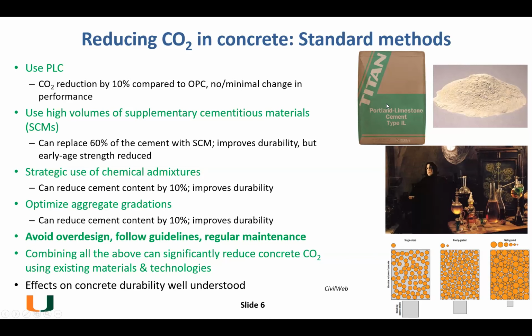A major technology is the use of cement replacements, known as supplementary cementitious materials. In principle and in practice, it's possible to replace about 60% of the cement with these materials. Most of them have emissions at most about 20% of cement, so you get a substantial reduction, up to 40-50%. The nice thing is they improve long-term durability and performance, but there is a drawback in that early strength is reduced.